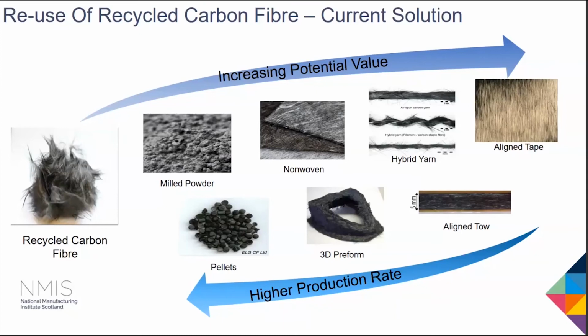On the other hand, the aligned short fiber prepreg tape has been developed by the University of Bristol, but because of the limited size of the material, it can only be applied on 3D printing or AFP machines. So in the end, there's another novel material that has been developed by the University of Nottingham. We can call it highly aligned short fiber tape. This can be converted to preform and prepreg, which can be easily engaged with high volume production lines, for example, compression molding. So I will use this material as a case study to explain the full story about carbon fiber composites recycling and reuse.